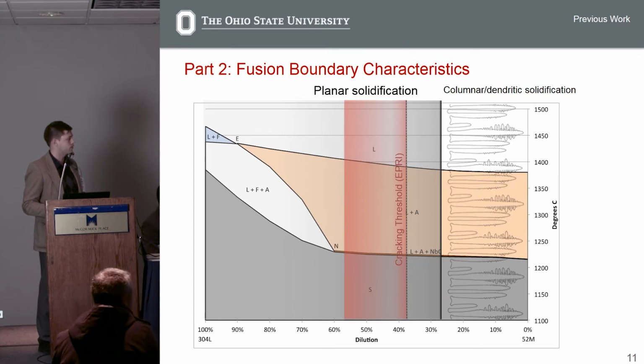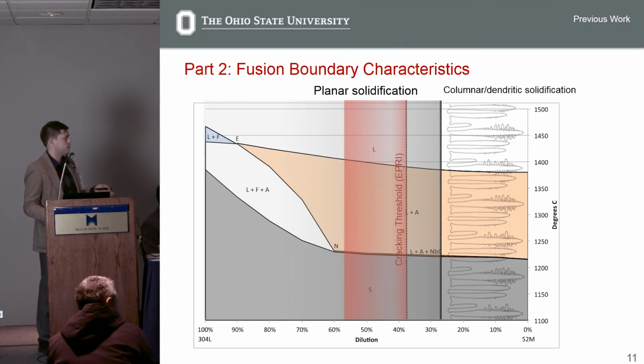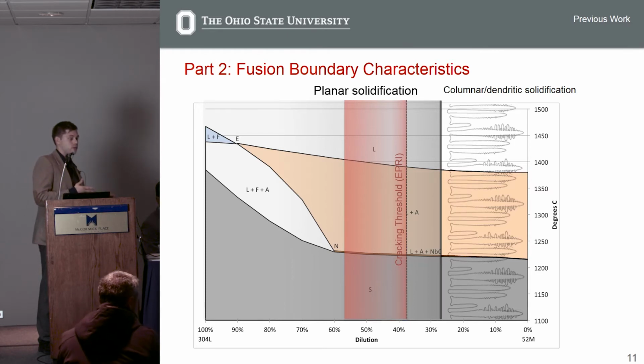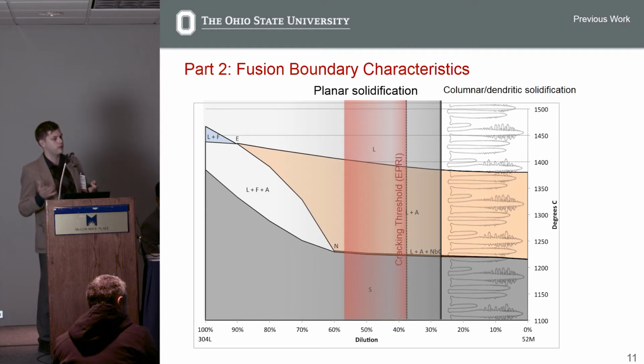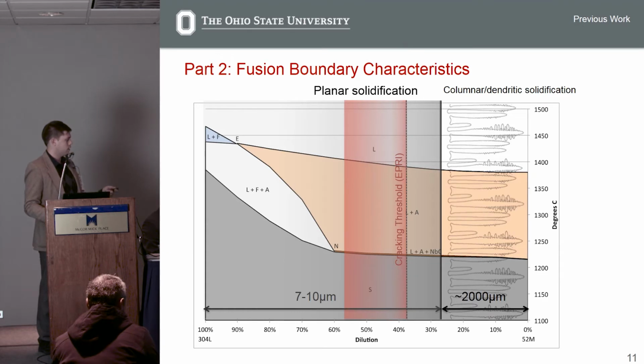So what we actually see in GTAW welds is that the planar front breaks down almost in the middle of this cracking threshold region, which indicates the microstructure that does exhibit the mechanism for cracking is also overlapping in a region that we know is solidification cracking susceptible. This isn't a coincidence. That's why the solidification cracking happens. And also the order of magnitude of these features is much different. As this metal solidifies from 100% base metal to about 28% filler metal, that happens over the course of maybe 10 micrometers, where the remaining 2.5 millimeters of deposition is almost 52M composition entirely.